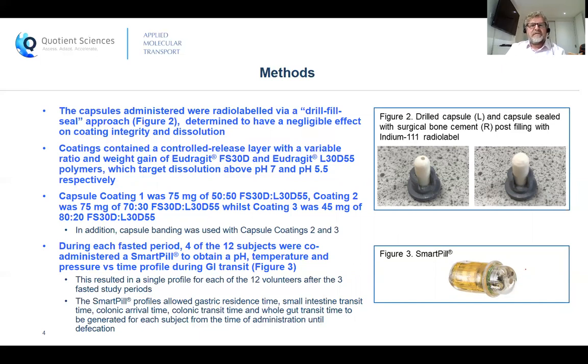Coating 1 contained a 50-50 mix of the 2 polymers and a 75 mg per capsule coating weight gain without capsule banding. Coating 2 had a 70-30 mix of the pH 7 to pH 5.5 dissolving polymers, also at a 75 mg weight gain, but this time with capsule banding, and coating 3 was an 80-20 mix of the pH 7 and pH 5.5 dissolving polymers at a lower weight gain of 45 milligrams, but also with capsule banding.